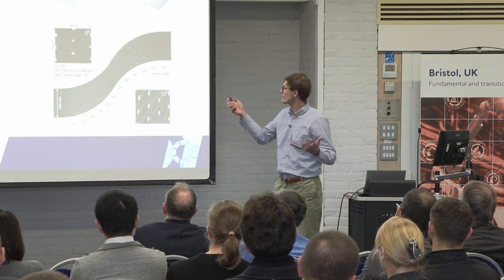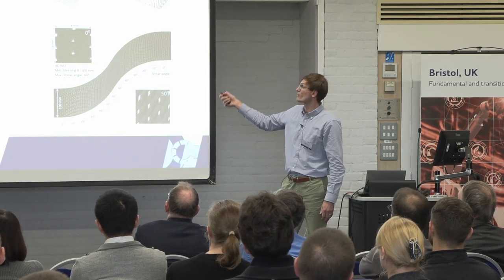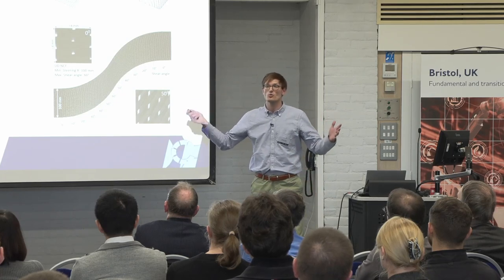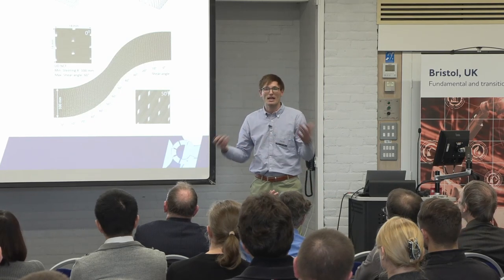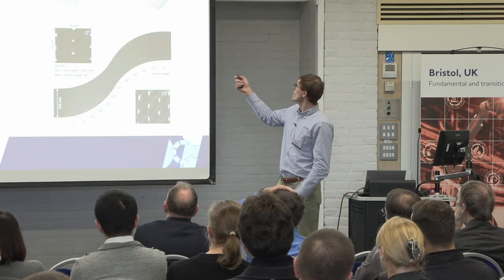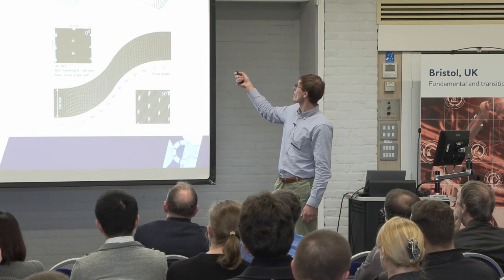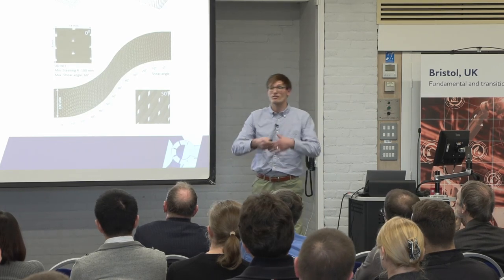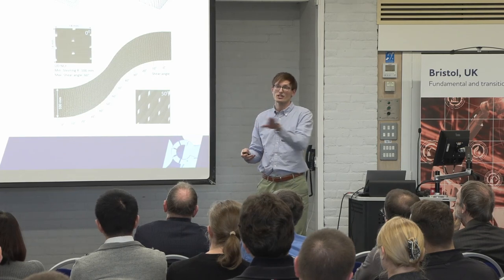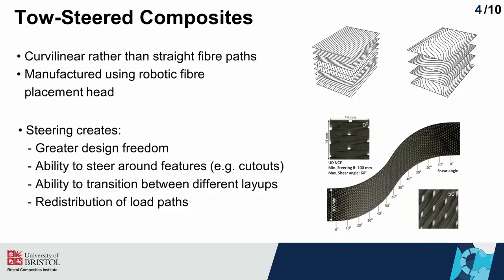Of course, everybody here is familiar with the classic straight fiber laminate. And all that we do with tow shearing or variable angle tow composites, as they're sometimes called, is we still have a laminate stack, but now every single layer can have a ply where the fiber orientation can be steered in curvilinear trajectories. This is typically done with some form of robotic head. And this is an example of a single woven tow course of the rapid tow shearing process.